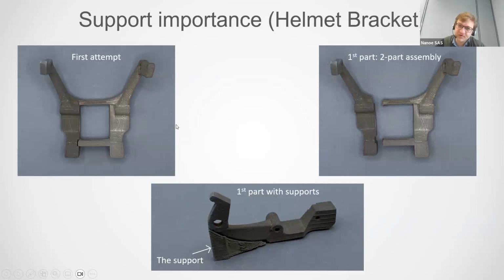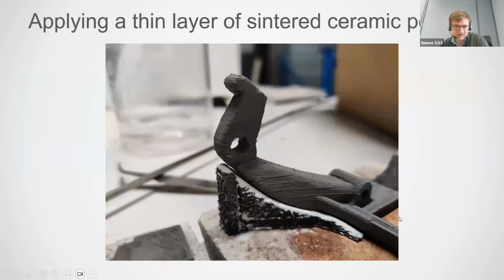Another example about support and printing strategy is this part which you can see here, a bracket that was asked for by one of our customers, the Royal Dutch Navy. The first difficulty we had was that the part was too big for our furnace. We couldn't fit it in the furnace. So we decided to cut it in two parts and assemble them. You can see here how we did that. We just separated it here, made it a self-assembling two-part structure, with some supports here. You can see here a thin layer of ceramic that is just added before sintering, so that you can see how it looks.